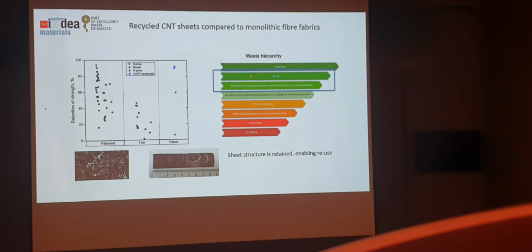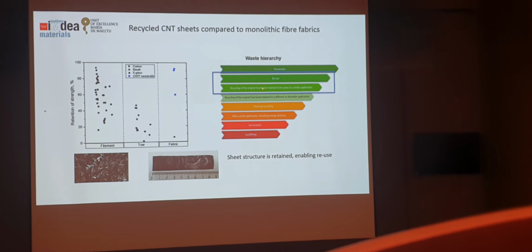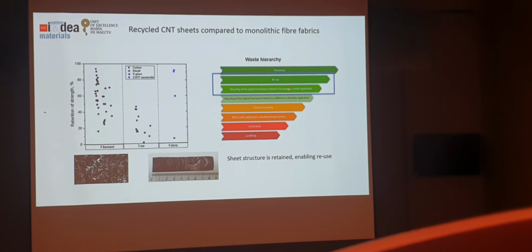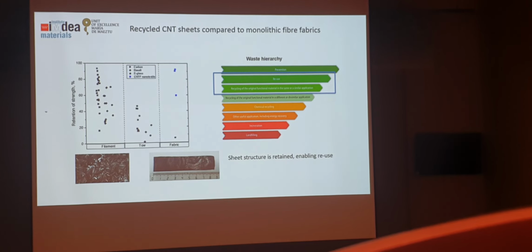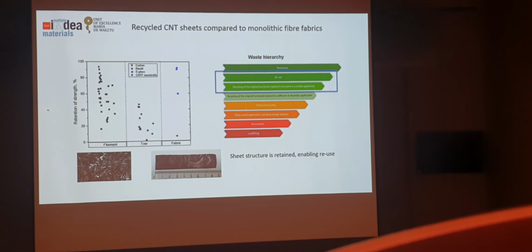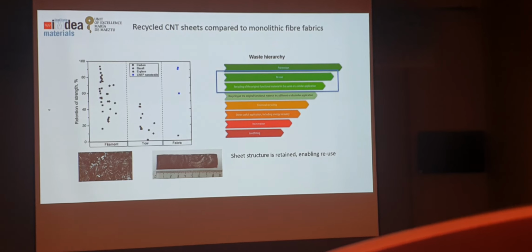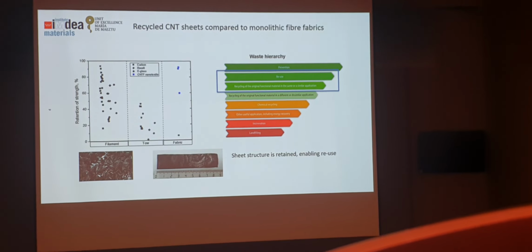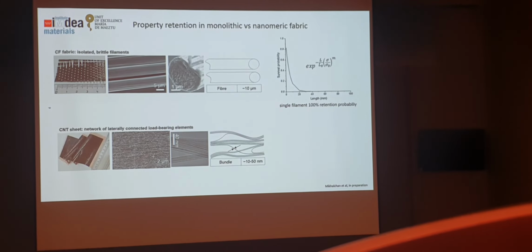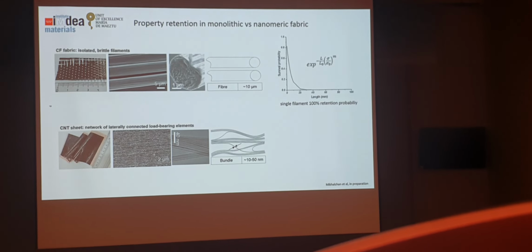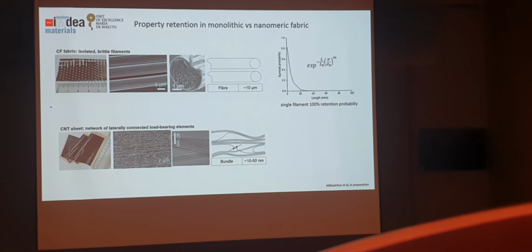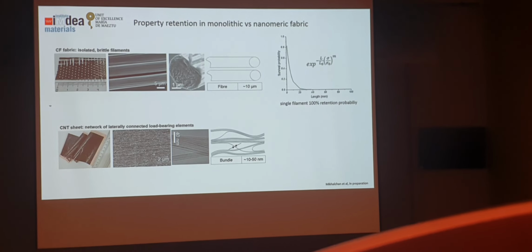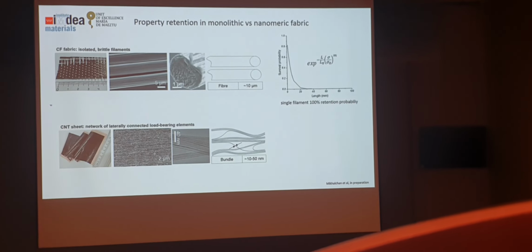So that's great news, because it means that within the scale of recycling, we really are seeing the best possible scenario, which is something close to either reusing or recycling for the same application. So with carbon fibers, essentially one ends up losing value because they get short and they have to be either chemically recycled or used for a lower grade application. Now, we'd like to understand this in more detail, particularly to see if this will apply to higher grade fabrics or CNT sheets as they become more available.